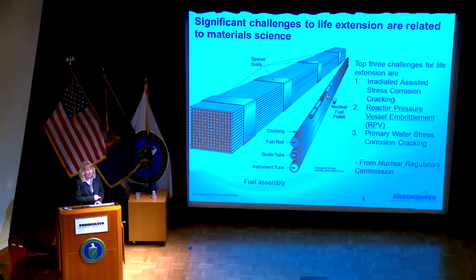I mentioned the stress corrosion cracking because I'll return to those later in the presentation, but just to describe how this phenomenon occurs, it's a combination of corrosion and stress being applied to the material simultaneously. So the material's in an environment that causes corrosion, a corrosion film forms, and then the material is stressed. When you apply that stress, it breaks the corrosion film and exposes bare material beneath. And then that material corrodes. And of course, you apply more stress, and so the process continues, and you get this slow, stable crack growth that's very damaging over time to the materials in a reactor.